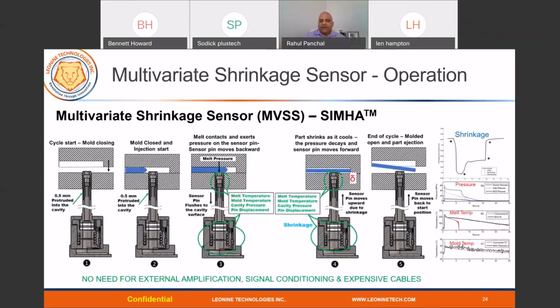Similar to the animation you saw during the single mode shrinkage sensor, as soon as the melt comes into contact with the IR temperature sensing unit, the entire sensor will move backward 0.5 millimeter. There is a hard stop, so at 0.5 millimeter it will stop, and the sensor remains put inside the cavity. As soon as the melt comes into contact with the sensor pin or the head, it will measure the melt temperature. It is continuously measuring the mold temperature too, and it starts measuring the cavity pressure throughout the molding cycle, and the same with the in-mold shrinkage.